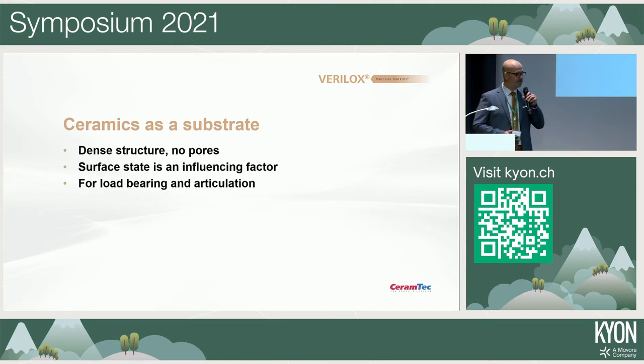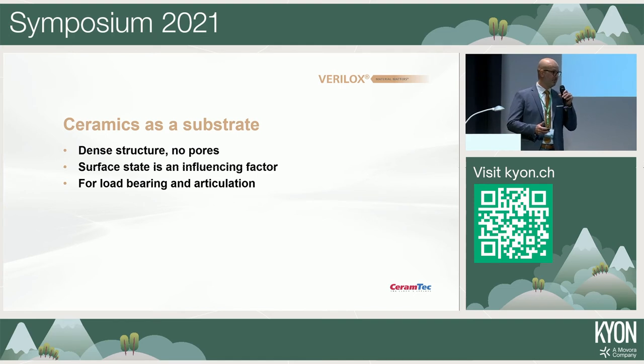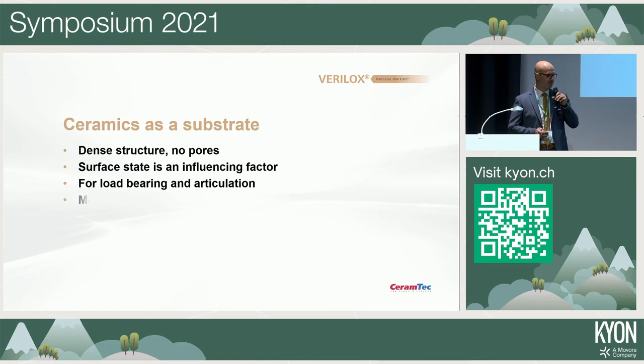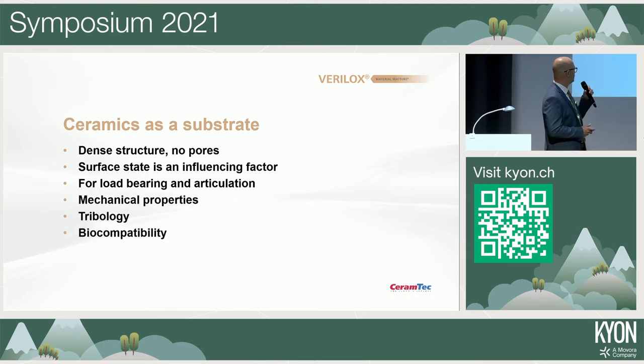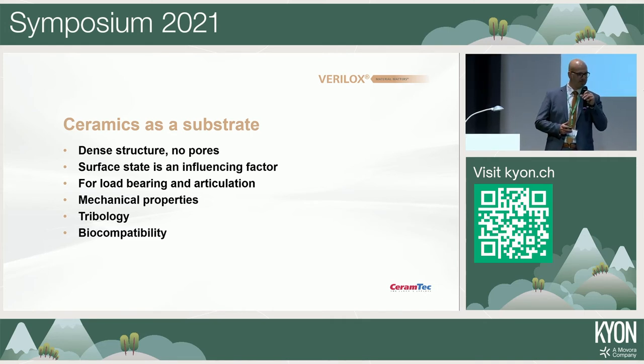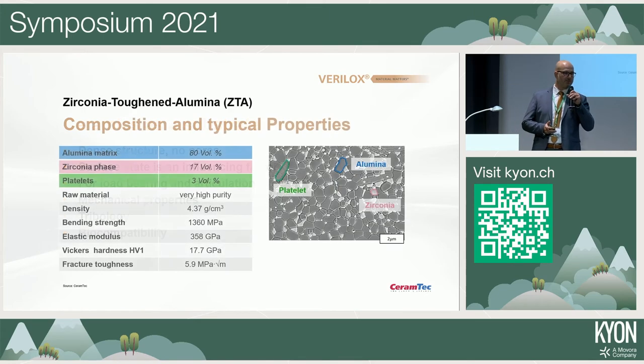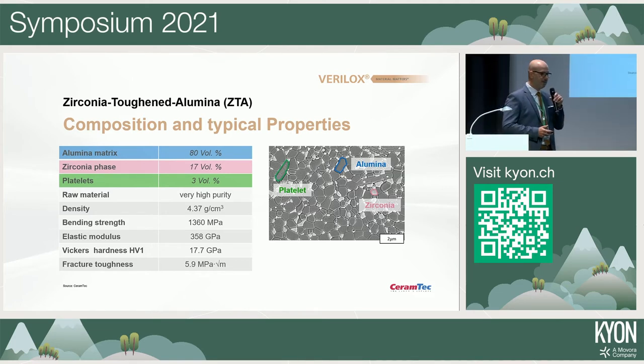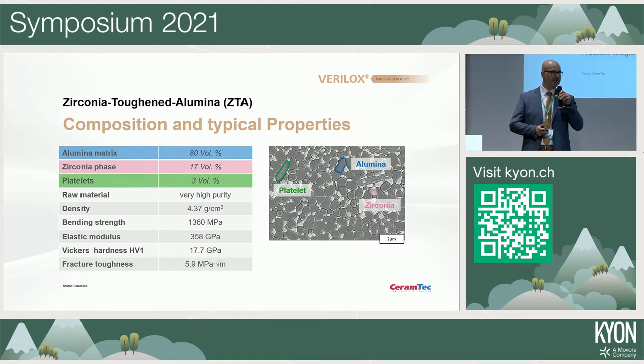As I said, if I want to use it as a substrate, I make it dense, no pores. What's important to know is that the surface state always has an influence on the mechanical properties, and we can use that material very well for load bearing and for articulation. And of interest for that are the mechanical properties, tribology, and not to forget, a very important factor, biocompatibility. But let's look at the material first like the engineers do. The composition of the pink stuff that I mentioned before is an alumina matrix as basis. Roughly 80% of the material is alumina grains. Then we have a so-called zirconia phase inside, that means zirconia grains, roughly 17 volume percent, which make the material stronger. And we also have platelets from other oxides, which also contribute to the strength of the material.